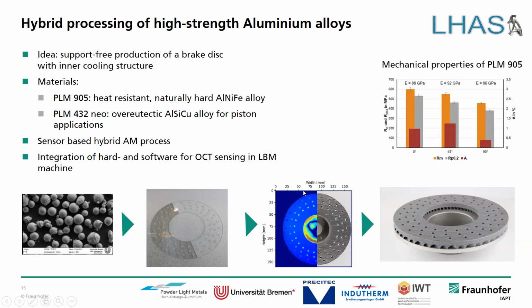And we achieved this by implementing an OCT sensor, so optical coherence tomography sensor, into our LBM machine. So including such systems here is also an aspect and a specialty, I would say, of the department. And well, the part is now also being tested. The brake disc is being tested at our industry partner. Characteristics: 600 megapascal ultimate tensile strength, 520 megapascal yield strength, and of course very much directed to strength, 1% elongation.